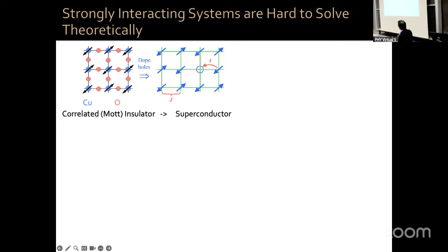Now, something very interesting happens if you remove a few of those electrons, right? Or you dope the system with holes. Removing a few electrons is like adding holes, we call it. So if you remove a few of these electrons, now there are some empty sites on your copper oxide plane, so the electrons are not repelled by an existing electron there, and they can jump. So there is this correlated dance of electrons where you jump between empty and occupied sites like this, okay? And this happens in such a way that almost magically gives rise to high temperature superconductivity.